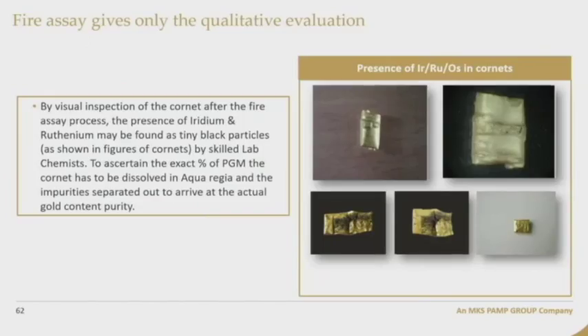So you can see in the picture that by visual inspection of the cornet you can identify the presence of a PGM, but to detect which PGM is present, you have to go for spectroscopic analysis, which is a little tedious job. The morning presenter already explained this. They have to take extra precautions for the assaying or detection of these three elements. You can see in the pictures that when these PGMs are present, the cornet looks different. You have strips on the cornet, you have blackish spots on the cornet, which clearly shows the presence of iridium, osmium or ruthenium in the samples.